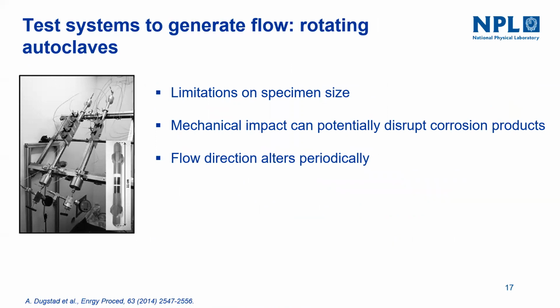But they have limitations on the specimen size because the weight determines the velocity. And also the mechanical impact could potentially disrupt corrosion products. And also you can't use this for testing stress corrosion cracking tests where the specimen is loaded to a stress corrosion cracking jig. And also the flow direction alters periodically.